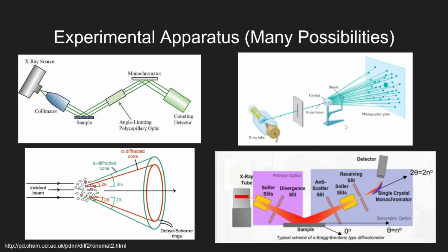So that ties back into the Miller indices. There are 3 different planes in this case that are associated with a distance of 1. So if A1 equals A2 equals A3, which it does in this case because this is a cube, then reflections from any one of these planes will be identical. There's no way to tell them apart, so you lose a little bit of information. If A1 does not equal A2, which does not equal A3, then you can perfectly preserve all information about all possible reflections. But in general, cubic loses the most information.